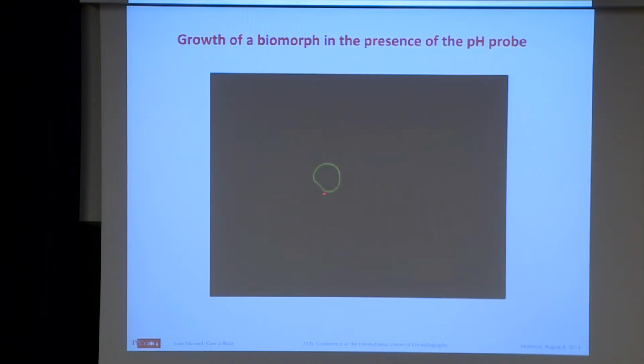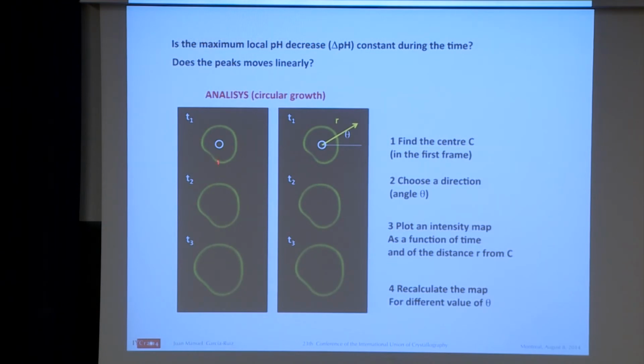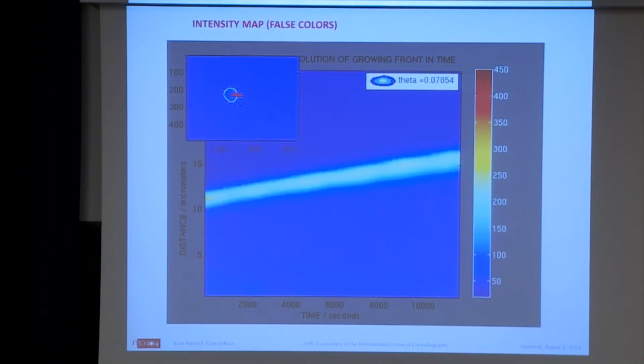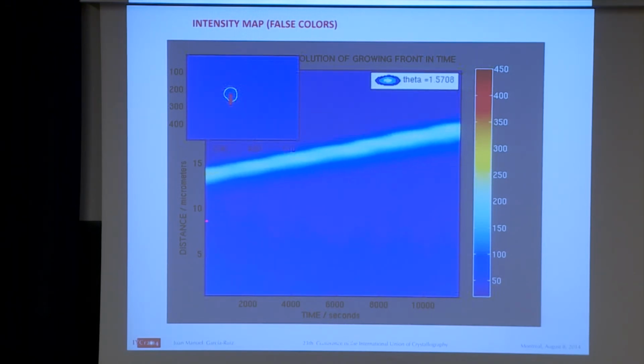This is a growth rate. This radial growth, okay, is before any curling. And then we measure the pH. So you can see that really the pH changes only in the growth front, not in the bulk, right? And by measuring the intensity of the pH around this, okay, we can see the distance as a function of time, this is the growth rate, right? But distance as a function of time, you can see that there is a variation.